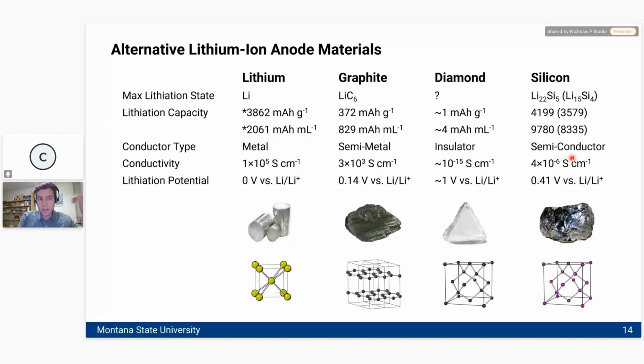Also, when you put lithium into it, not only do you get a relatively large amount of lithium, these are the metrics here. This is the lithiation capacity in units of milliamp hours per gram in this line here. Far, far more lithium goes into silicon than into graphite on a per gram scale, even though silicon itself weighs more than carbon. Also, you get a really massive density of lithium in silicon on a per volume scale. This number, 9780, is in units of milliamp hours per milliliter. It's way more lithium than you can squeeze in when it's all by itself. So bulk metallic lithium has a lower amount of lithium per volume than silicon.